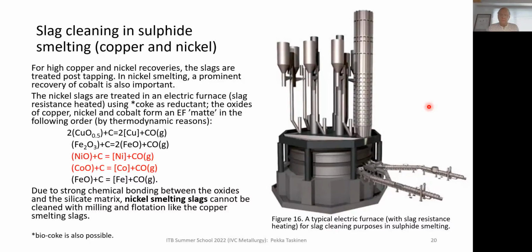And that means that we are using some reductant, here carbon, which is today the standard reductant in nickel smelters. In future, probably it will be hydrogen or biomethane, so biologically generated methane gas, which is non-fossil fuel, like hydrogen, as a reductant.